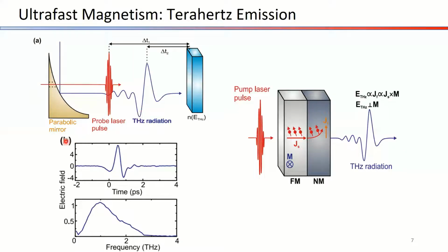And this is the kind of result of the terahertz emissions. This is the electric field as a function of time. You can see when they emit, they have the peak at this time. So you can see the time when they emit, and from this time domain we can also get the frequency domain in the terahertz range, using the fast Fourier transform, or FFT. From this frequency domain we can see how much frequency our sample has, in this range, larger or smaller, so we can see the frequency domain of the materials from this